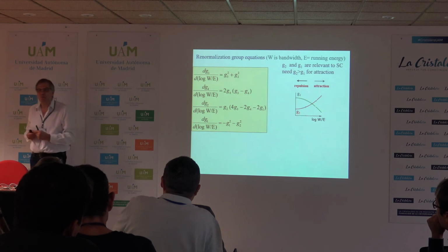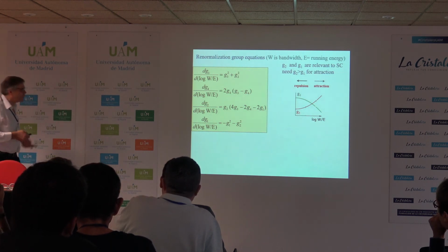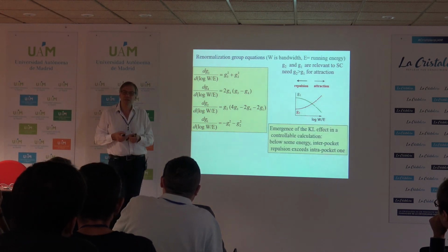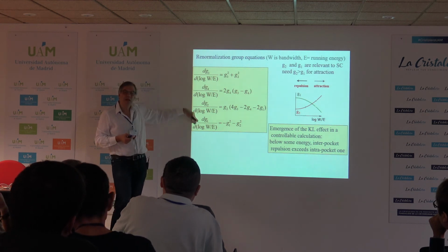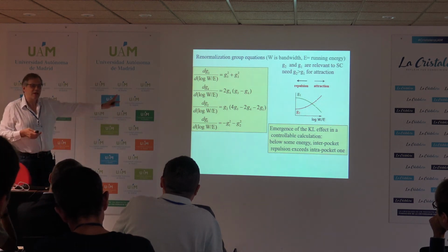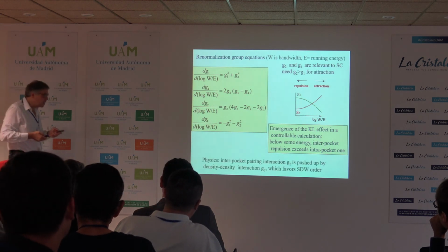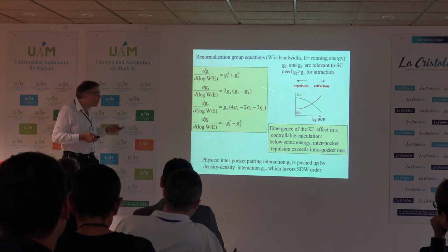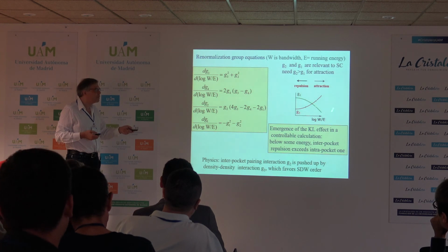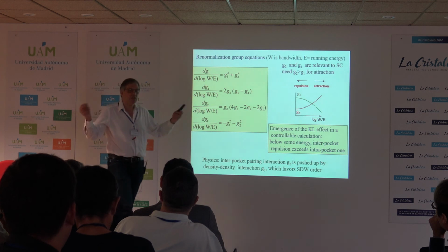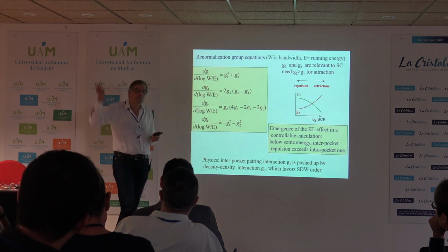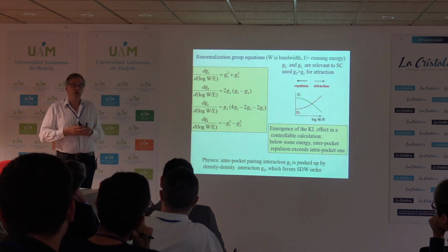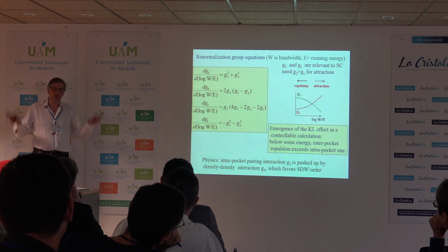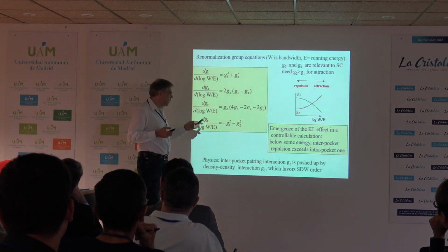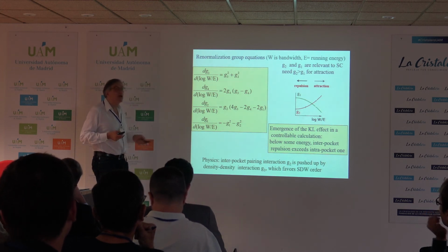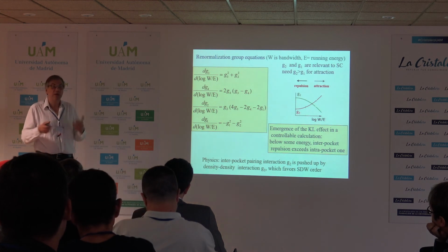It's a wonderful story which happens in all problems, including graphene, where you get d plus id because of this. And this is nothing but enhancement of the Kohn-Luttinger effect in a controllable way. This is a controllable approach. You still assume that all non-logarithmic terms are weak, but logarithmic terms you include explicitly, and this is what you get. And the physics is interesting. You can ask, what happens here? Why does G2 go up and G1 go down? Because interaction between pockets, or patches, whatever, is enhanced by an interaction that grows by itself. And that interaction will give you spin density wave. So if you look at this, you find exactly what happens: as the system tends to develop spin density wave instability, it also tends to convert repulsive interaction into attraction, which is another way to say that at the end of the day, spin fluctuations promote superconductivity.